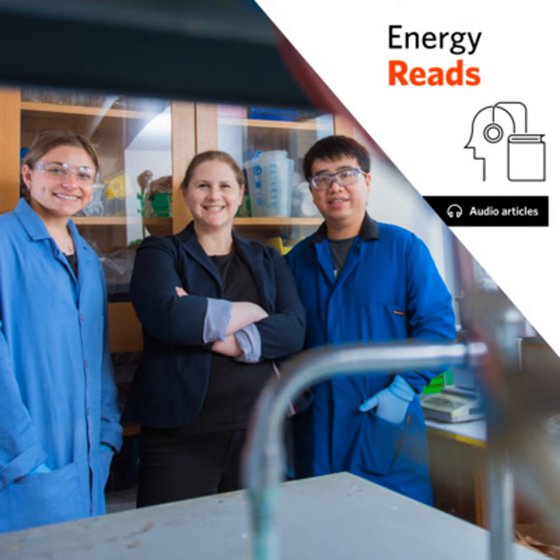Better still, the two strands can be detached from one another. "The connection is stable, but if we heat it up, we can remove the secondary strand that has the catalyst on it," says Furst, "so we can dehybridize it. That allows us to recycle our electrode surfaces, without having to disassemble the device or do any harsh chemical steps."